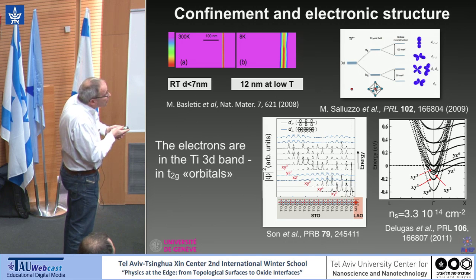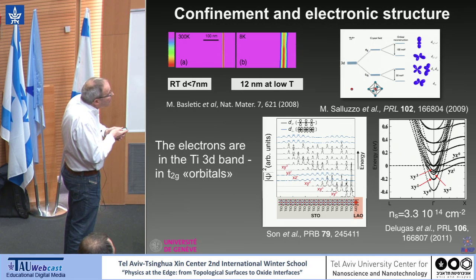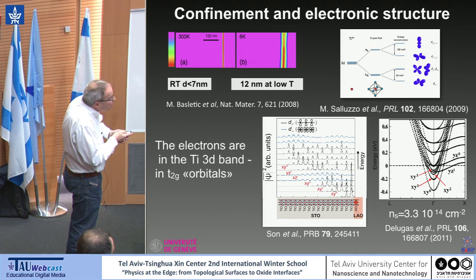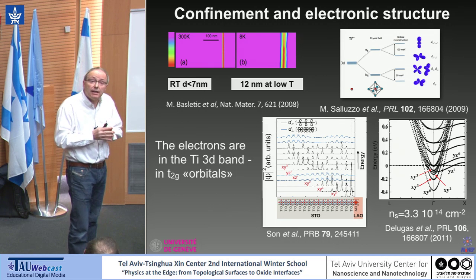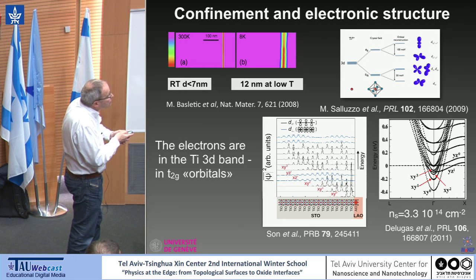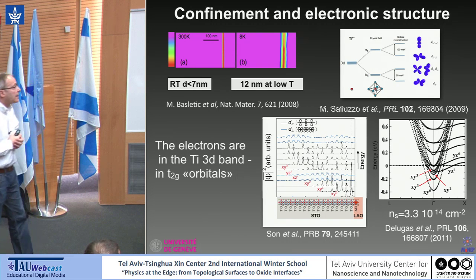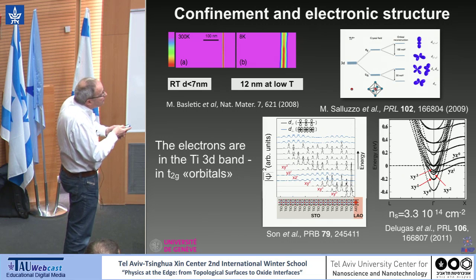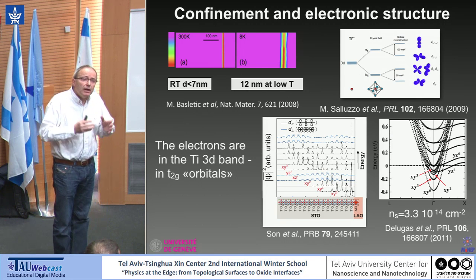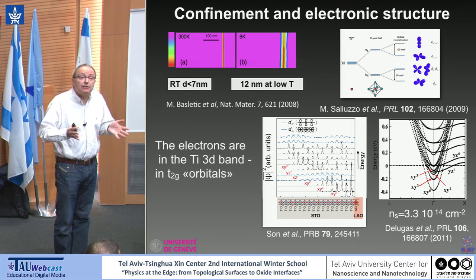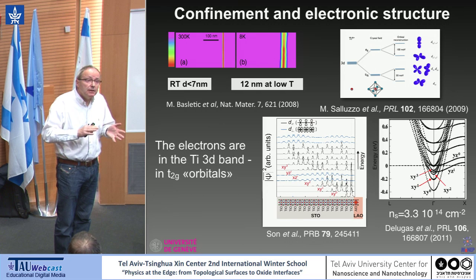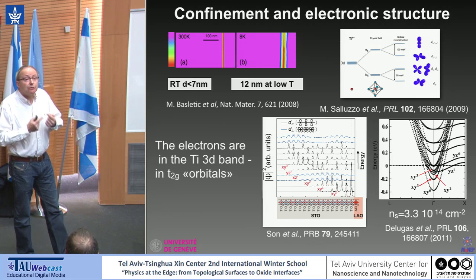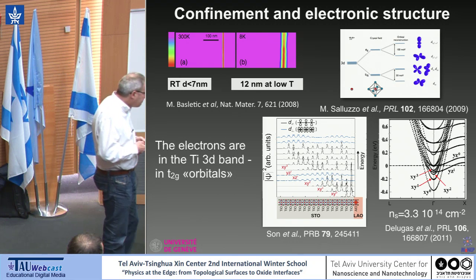Now, if you look in space at the extension of these different electronic bands, you see here lanthanum aluminate. This is strontium titanate. This is energy. And you see here now the wave function squared. For the lowest one, you see that these electrons are very localized spatially at the interface. And when you move up in energy, the electrons are going deeper and deeper, and the xz, yz are going deeper than the xy. You also see that the probability to find electrons is localized on the titanium. So it is quite different from a free electron gas, where you would find some envelope function. And this is why we prefer to call this system a 2D electron liquid rather than a 2D electron gas. OK, so let's keep this in mind.